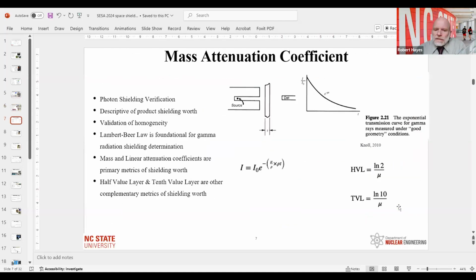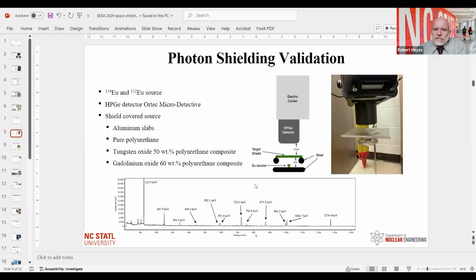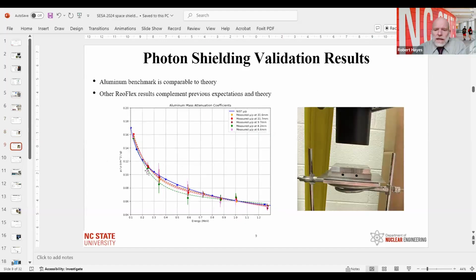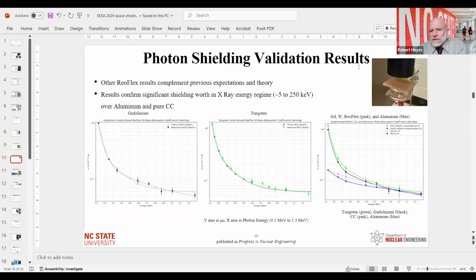The Lambert-Beer Law for radiation attenuation. This is the actual experimental configuration where we're taking a europium source with these energy lines down here and putting it underneath the high purity germanium detector to measure radiation attenuation. There's the benchmarking where we're using aluminum plates to demonstrate that it works as expected for aluminum plates. And then here's when we're testing the actual conformal coat, the measurements. You can see the difference for the lower energy x-rays, how much better the radiation attenuation is because you've got the high Z metal oxide present.